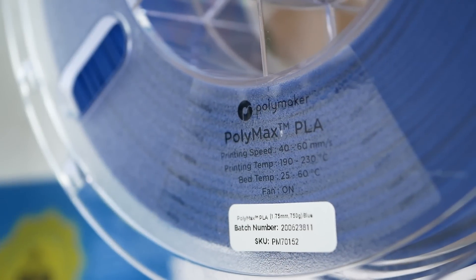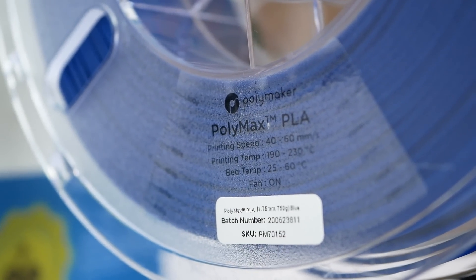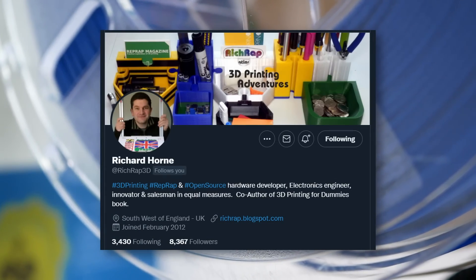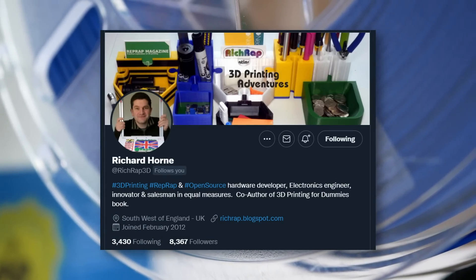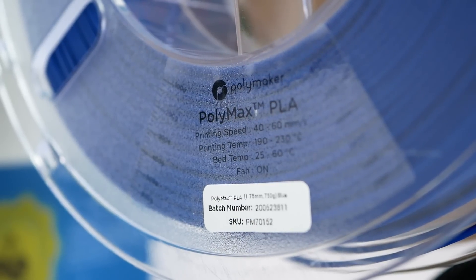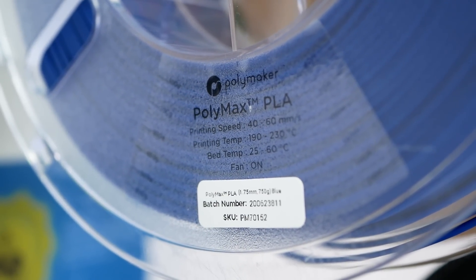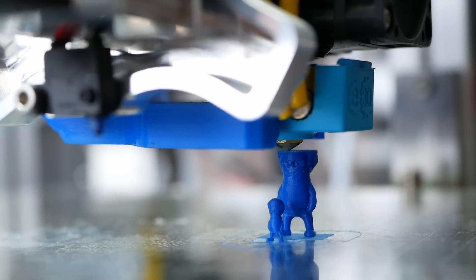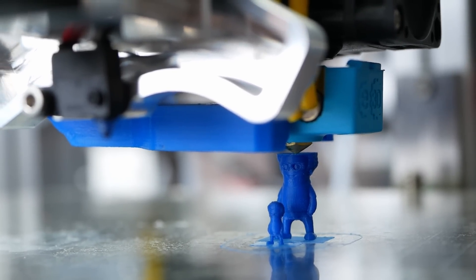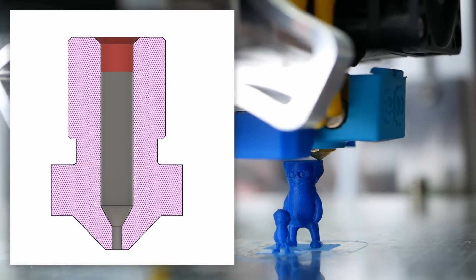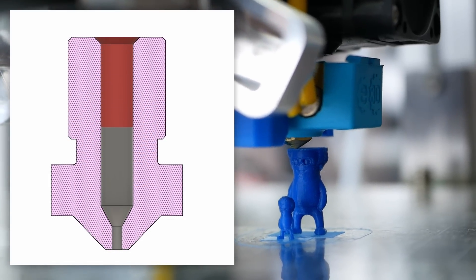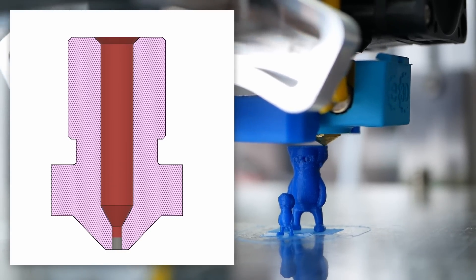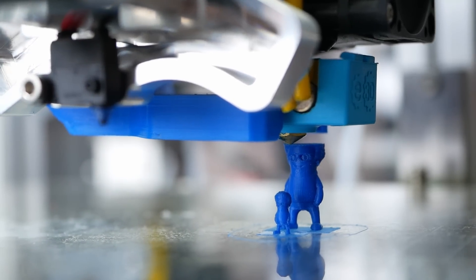I used Polymaker's Polymax PLA because Richard Horne aka RichRap recommended it to me. He did a bunch of similar tests a while back and was kind to share his experiences. Using the right material for these tiny nozzles is quite important. If any particles are in or on the filament that are too big, the nozzle will clog. Then the material can't decompose too fast. Because we extrude so slowly, it takes around 10 minutes for the material to travel through the melt zone, whereas with regular prints, it only takes 10 seconds.